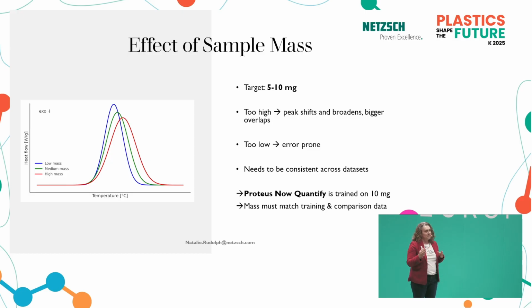But what I want to talk about is what can all be influencing factors on a DSC curve. The first I show here is the influence of sample mass. It depends how much you put in your machine. For one and the same material, a low mass will produce a more narrow peak, a high mass, a more broader peak. Broader peaks are bad for us because overlapping peaks will be harder to distinguish. So too high, the peak becomes too broad, too low, we have errors. It's one of the same material and it can produce this difference in a curve.